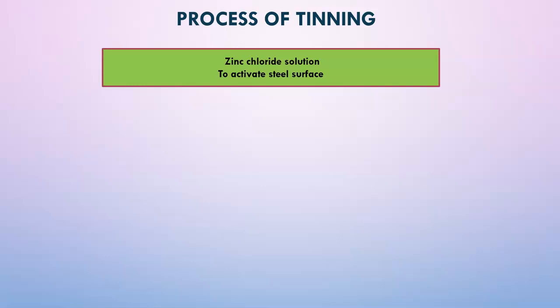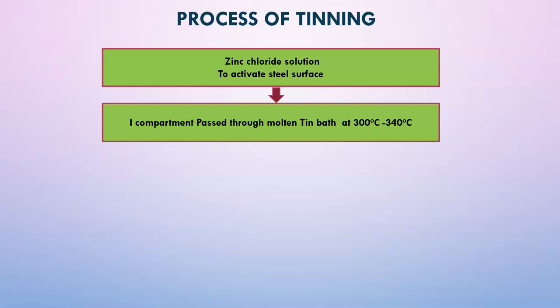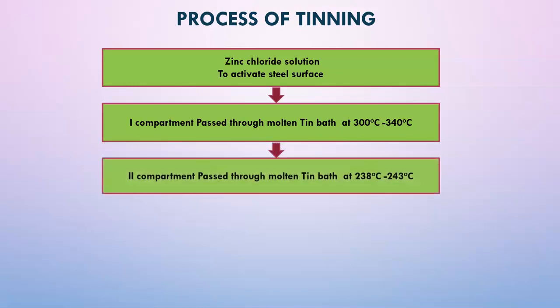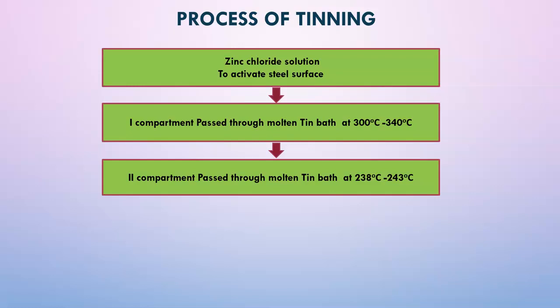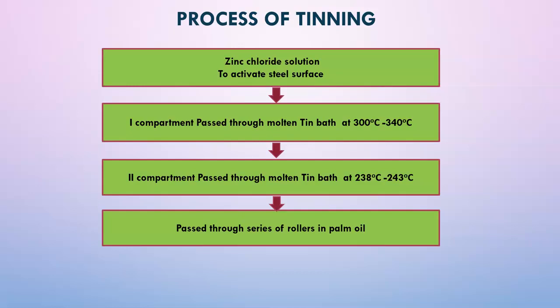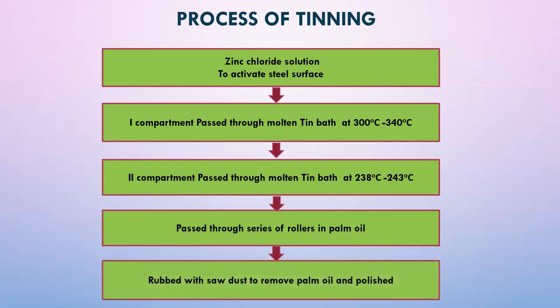The prepared sheet is dipped into a bath containing zinc chloride solution, and then it is dipped into another bath where molten tin is maintained at a temperature of 300 degrees Celsius to 340 degrees Celsius. The sheet then is removed and dipped in another bath which has molten tin maintained at a temperature of 238 degrees Celsius to 243 degrees Celsius. Then it is removed and passed through rollers in palm oil to remove any excess of metal, and the palm oil is removed by rubbing it with sawdust, and then the sheet is polished. And now we have a tinned sheet of iron.